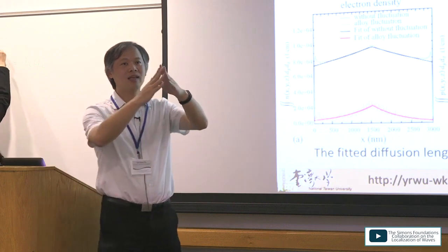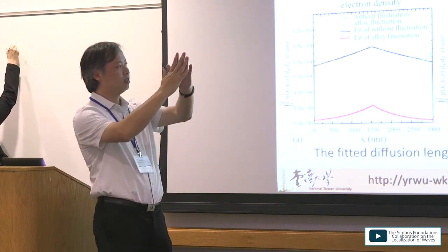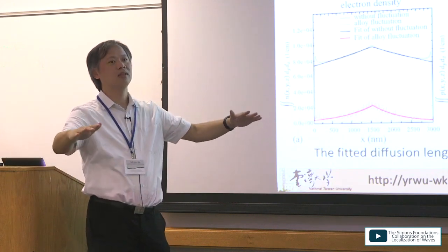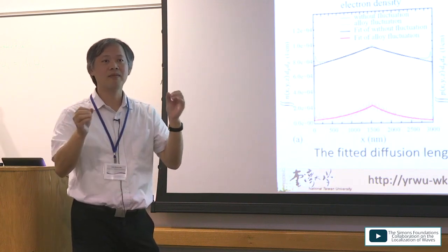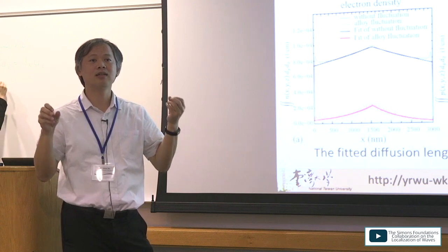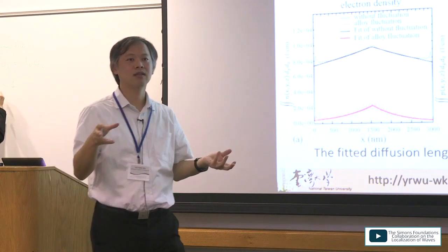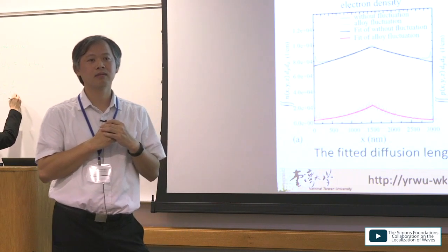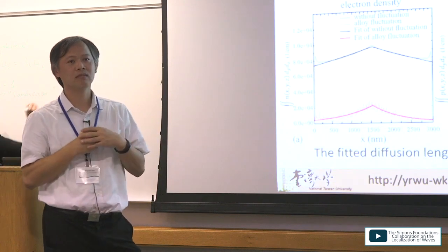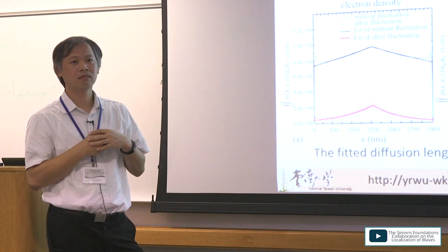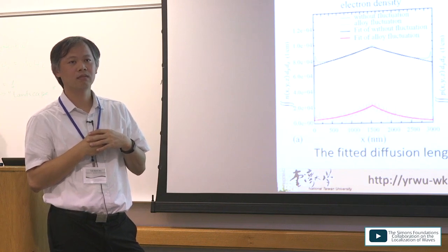In gallium nitride, if you don't consider fluctuation, your diffusion length is longer. So if you have a very high density of dislocations, you have a very high possibility to be captured by the defect. Right, so my question is, is that consistent with what's known experimentally? I thought pure gallium nitride quantum wells had a higher efficiency than InGaN, but maybe I'm wrong about that.